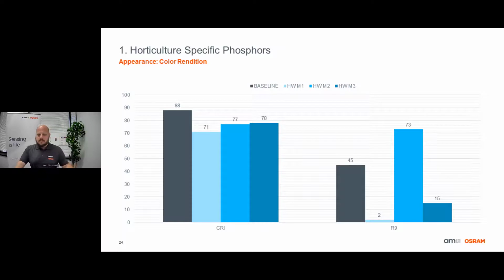Now, for those of you who are not familiar with CRI and R9, the R9 value represents the source's ability to render red. And this could be important for crops like tomatoes or roses. All four of these solutions have an R9 value that's greater than 0. And that is the typical minimum value for a traditional 80 CRI white. Yes, R9 can go negative. However, R9 doesn't tell us much about the way the source is rendering red. So if we evaluated these spectrums using TM30, we would find that the low R9 value for the M1 solution is due to the fact that it's actually undersaturating red, whereas the low R9 value for M3 is actually because it's oversaturating red. So under the M3 solutions, red would look very bright, bold, and vibrant.